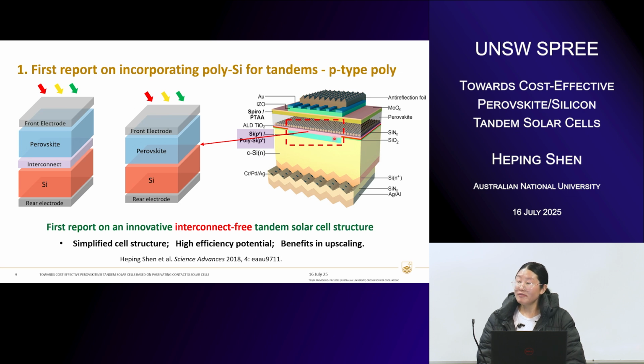And this structure is very interesting and also very attractive in terms of a few different aspects. First, it simplifies the structure, right? We don't need to deposit any tunneling junction. We don't need to deposit any TCO layer. We just place the two cells together. So it simplifies the cell structure. That means it can possibly reduce the cost. And second, it can have a higher efficiency potential by eliminating the potential parasitic absorption loss from the tunneling junction or TCO layer. So this is proven by the high efficiency we were already able to achieve.